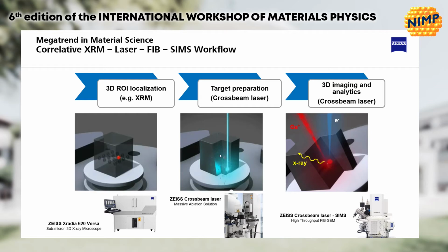We read out this 3D information from the ROI with the laser inside the FIB, and then started to cut everything around the area of interest just to analyze the surface. And finally, we image the surface and analyze the surface with the crossbeam. And at the end of the experiment, we performed from this given surface a mass spectrometry analysis and correlated these results with the high resolution images.